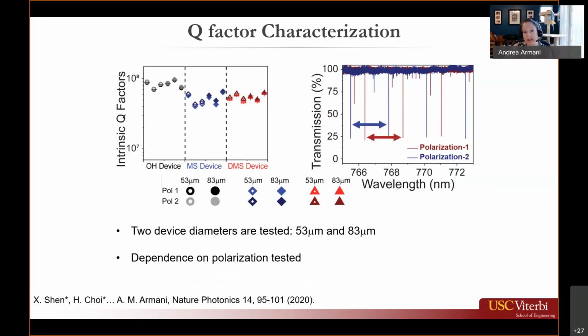So the first thing we did, again, was to measure the quality factor. We actually looked at 2 different device sizes. So we looked at devices that had 53 microns and 83 microns in diameter. Because circulating power is dependent on device diameter, we wanted to make sure that the device diameter wasn't an additional confound in our experiment. So that wasn't playing a role in our experimental results.